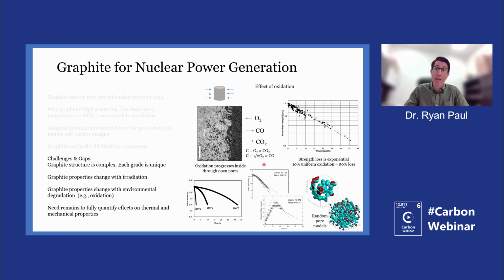There could be, in an accident scenario, perhaps air or steam oxidation of a graphite component. Because of the open pore structure of graphite, the oxidant can get inside of the graphite pores and attack not only the surface, but through the open porosity, attack the walls of the pores at some depth, sometimes several millimeters or more inside the graphite. So there's an overall attack and oxidation or gasification of the graphite, which is temperature dependent and microstructure dependent. But also there's simultaneous irradiation occurring, which is only really beginning to be studied more in depth.